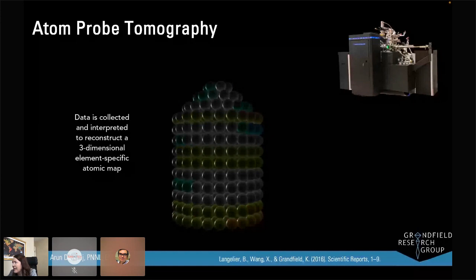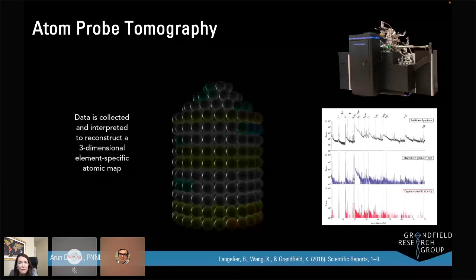So we've applied this technique to look at bone structure. It's a mass spectroscopy technique. When we record the raw data, you'll see something like this graph on the right with many peaks showing all of the different mass to charge ratios of each of the ions and molecules that evaporate off of the sample. By doing some data analysis, we're able to separate out the signals representing bone, including the organic phases such as collagen and the mineral phases such as hydroxyapatite, and create a three-dimensional map showing the location of each of these species.